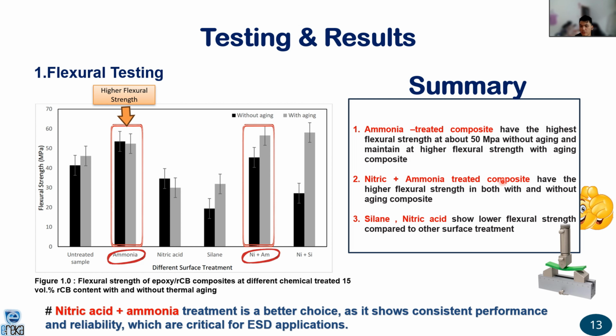However, when the silane and nitric acid are combined together, they show a lower flexural strength. So from here we can see that the nitric acid plus ammonia is a better choice because it has consistent performance and reliability, which is important for the ESD application.